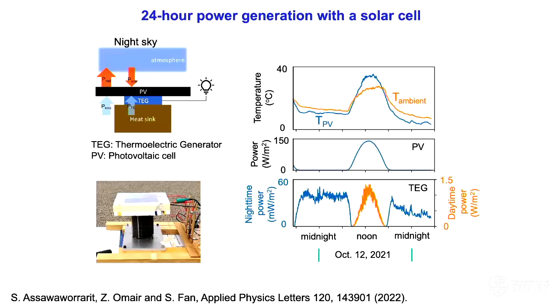So in this experiment, what Sid did is he put a thermoelectric generator at the backside of a standard silicon photovoltaic cell. And then he just measured the power from the photovoltaic and from the thermoelectric generator. So during the daytime, which is, let's say, around noontime here, you see power coming out of the photovoltaic cell. In this case, the photovoltaic cell is hotter than ambient, so you also see a little bit of power coming out of the thermoelectric generator, so it can boost up the power a little bit.